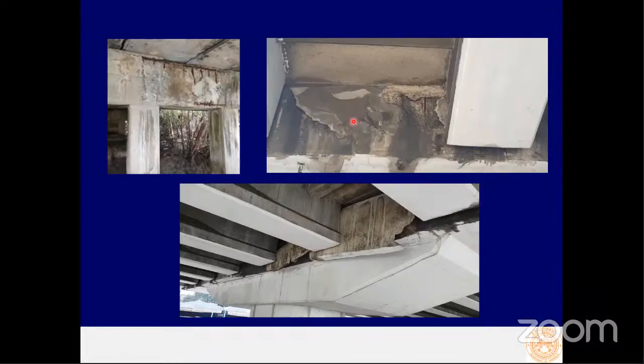And since we have a limited inspection budget, sometimes after a few years the corrosion forms and breaks the concrete and causes concrete delamination. So that caused a problem for us. So for this type of bridge, nowadays we have launched a project to repair those bridges for better and long-term performance.